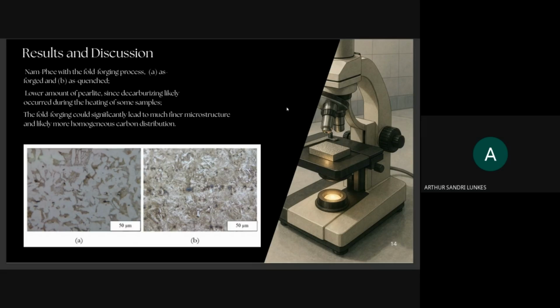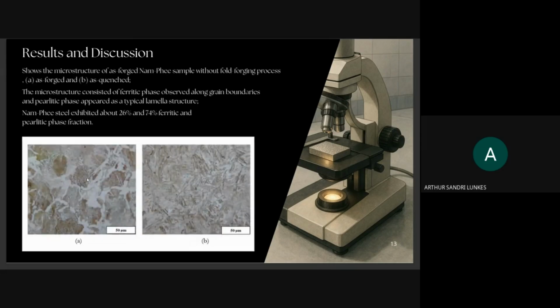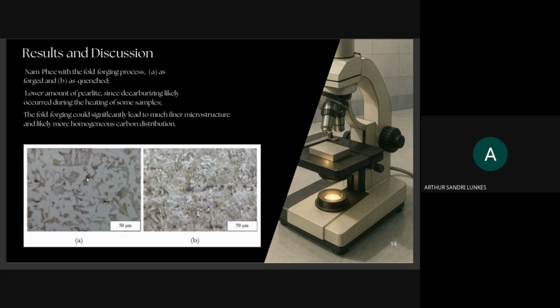So in this picture here, we have the Nam Phe steel with the fold forging process. This one here is only forged, and here we have a quenched process. For this process here, the fold forging process applied to the Nam Phe steel is decarburizing. Because of this reason, this sample here has less pearlite than this one here. Okay. The fold forging could simply lead to a much finer microstructure and a more homogeneous carbon distribution. So if we compare this one here to this one here, it is more homogeneous because of the fold forging process.